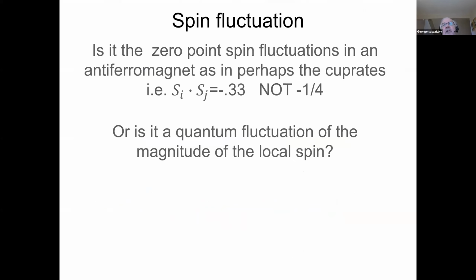So if you have a spin 1/2 system in 2 dimensions, antiferromagnetically coupled, then the nearest neighbor spin-spin correlation function is minus 0.33, right? But in Ising, if you didn't have the quantum fluctuations, it would be minus 1/4, minus 0.25, okay? That is the kind of spin fluctuation where one spin flips up and the other one spins down.